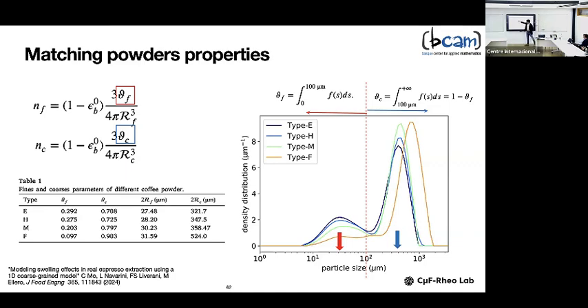In order to know the volumetric fraction of fines and coarses, you just take a threshold and integrate the distribution function for sizes smaller than 100 micrometers. This will be the fraction occupied by fines, and the other area will be the fraction occupied by coarses. With these parameters that you obtain, you can run simulations for different powders.